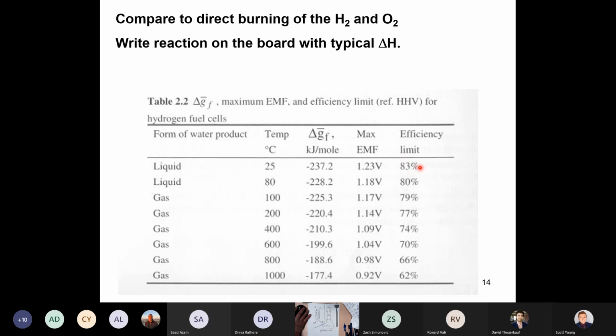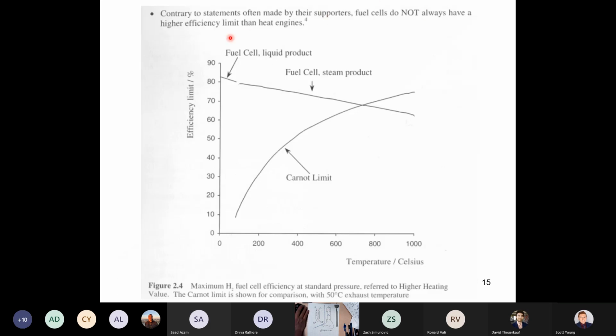And this becomes worse as the temperature goes up because the voltage drops with the fuel cell and your comparison to direct burning gets worse and worse the higher the fuel cell operates. So at some point, you know, you may win by just burning the hydrogen and the oxygen. But there's a limit to how much energy you can extract by burning, and the limit is the Carnot limit. So if you have the cold reservoir of the heat engine at room temperature and the hot reservoir at excessively higher temperatures, this shows you the efficiency limit that you can reach for a heat engine.